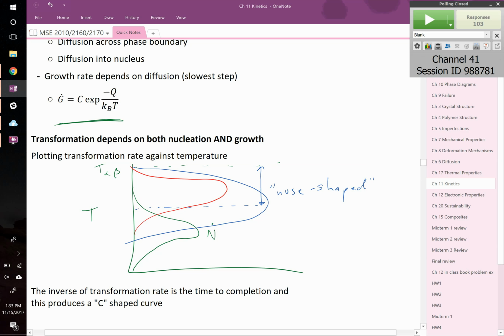Or in other words, if you go just a little bit below the melting point, it's not going to transform very quickly. And if you quench it really aggressively down to, say, room temperature or really low temperatures, it's not going to transform quickly either because you won't have enough energy for these things to grow. So because of that, you can actually quench phases and make them metastable, right? You could quench it, you could drop it so quick down in temperature here that your rate of transformation, the blue curve there, your nose-shaped curve, is essentially zero, meaning it's not transforming at all. So the metal alloys that we brought into class, that's basically what we did there. We quenched them into ice water, and they weren't transforming at all quickly until we held on to it in our hand, and we brought it up in temperature somewhere around here where it had an appreciable rate of transformation. Okay? Any questions so far on this?